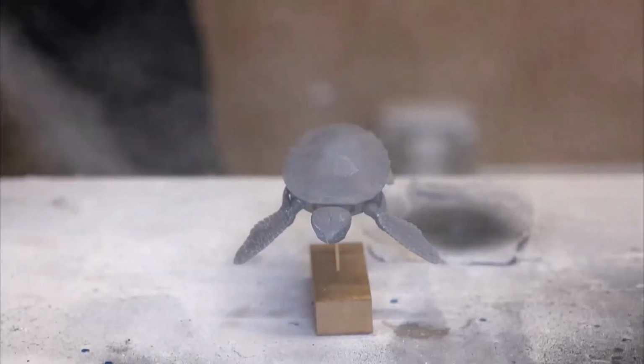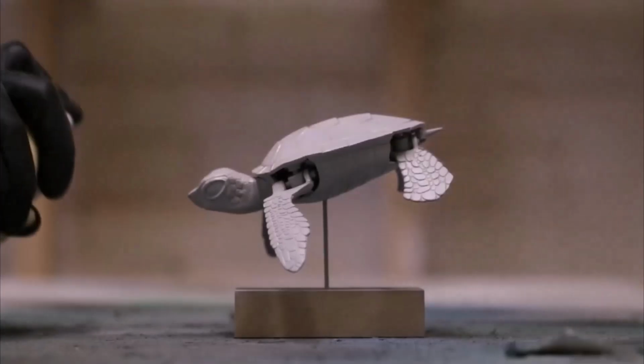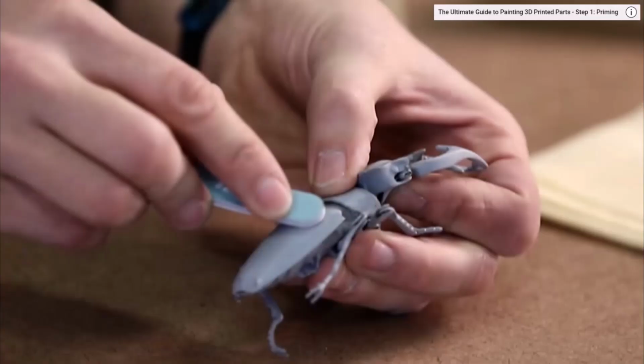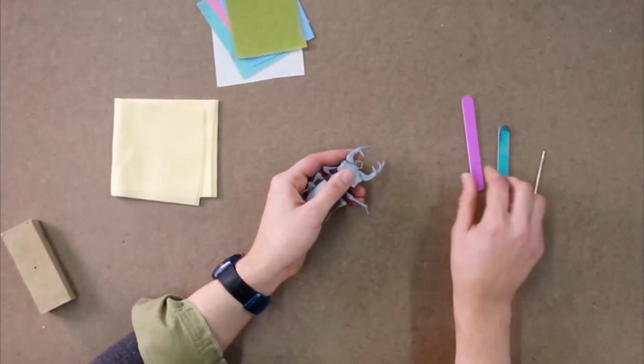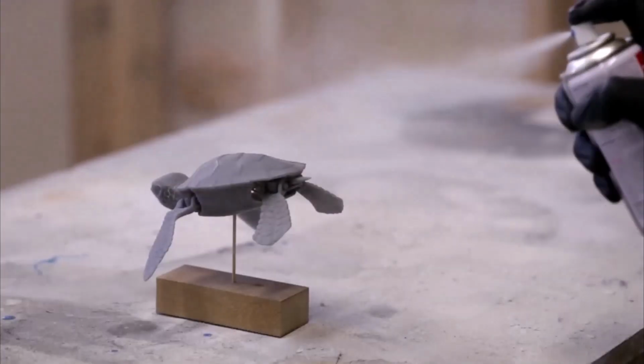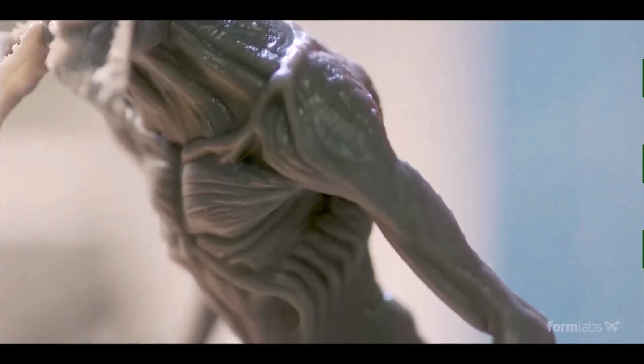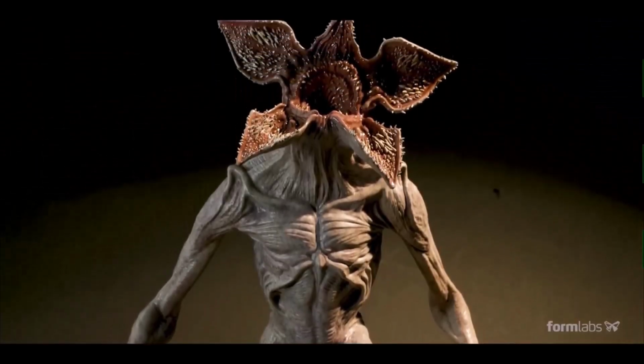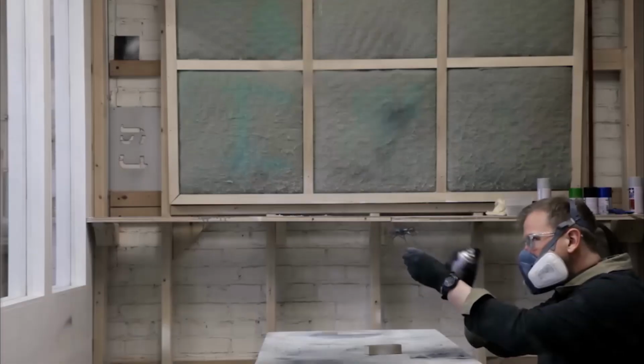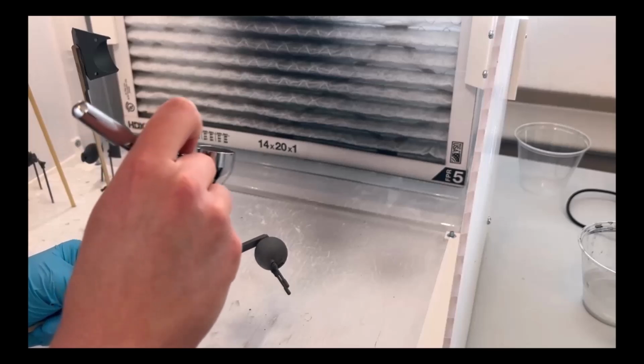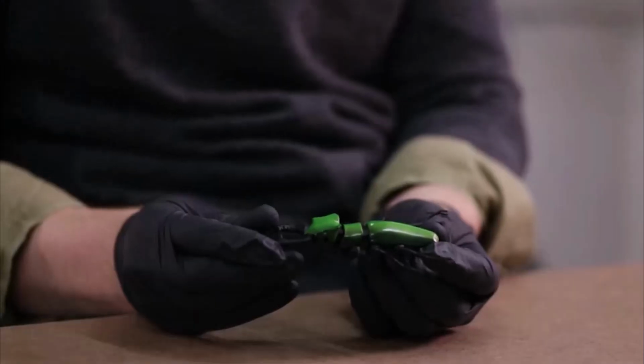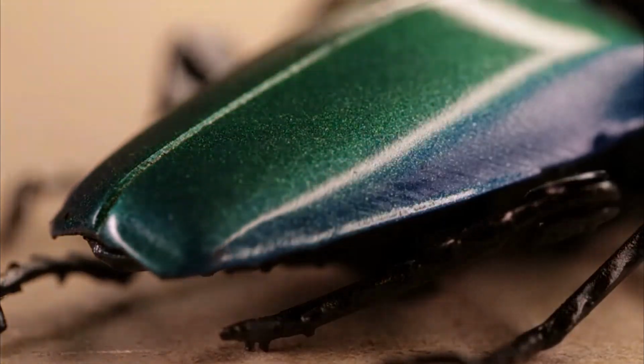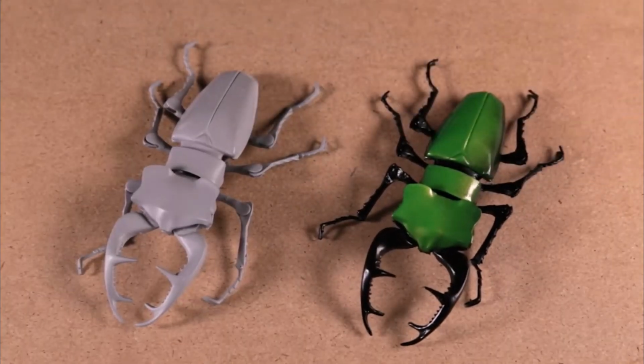Spray the primer on in even strokes, keeping distance away from the part to avoid paint runs. Once the primer has cured, review the surface and make any corrections necessary. You can always add another layer of primer afterwards. Just note that fine details can vanish with added paint layers. At this point, you are ready for painting. Spray cans, airbrushing, and hand painting in acrylics, enamels, and lacquers are all great ways to color your printed part. Once finished, let the paint dry and consider adding a clear coat to seal the paint and increase its longevity. UV clear coats are great for protecting SLA prints in outdoor applications.